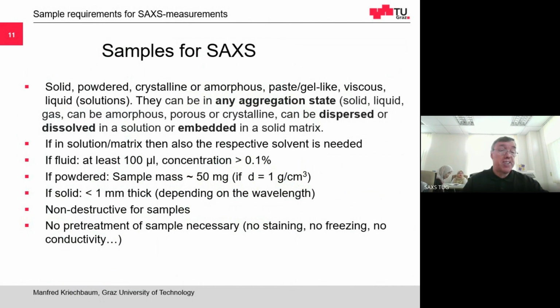Which samples can you investigate by SAXS? You can investigate solid, powder, crystalline, amorphous, paste-like viscous samples, liquid, even gaseous samples. So this is a big advantage to crystallography, because in crystallography, you have to crystallize your samples before you study them. Here you can use any aggregation state, and you don't have to do any preparation. You don't have to stain it. You don't have to freeze it or make it conductive. So it can be used as it is. The sample amount is very little, so you can measure 50 milligrams or 1 microliter. The thickness, if you have solid samples, should be around 1 millimeter. And it's a non-destructive method, so after the measurement, you could reuse your sample for some other experiments.